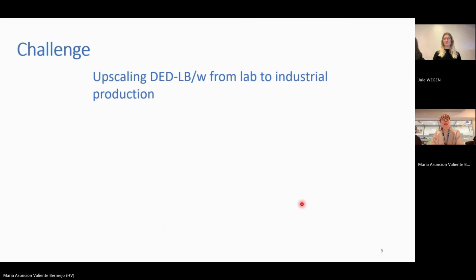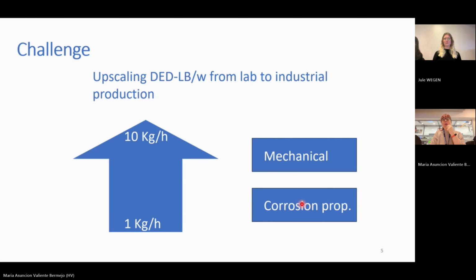So the challenge, as Jörg and Peter also mentioned, was to upscale this DED laser beam wire process from the lab to industrial production. Initially, what we wanted was to jump from 1 kilo per hour deposition rate to 10 kilos per hour. That was the initial goal, and we wanted to maintain equal mechanical and corrosion properties. So we were very ambitious on this. And in the end, we ended up around 5 kilos per hour, as Peter mentioned.